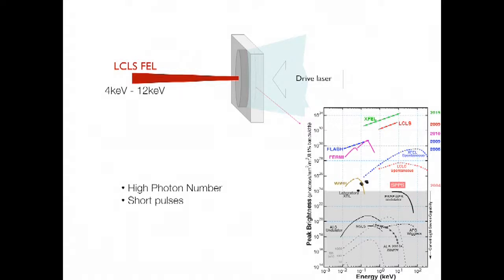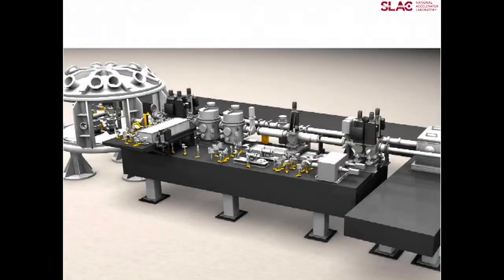And then LCLS at MEC, it's a hard X-ray instrument, so we use X-rays from about 4 keV to 12 keV mostly. Most of our experiments are around 8 and above to probe what happened in these materials. And this short, very bright source has really revolutionized this field and opened up a lot of areas for experimentation. So this is an overview of our hutch, a nice CAD drawing.